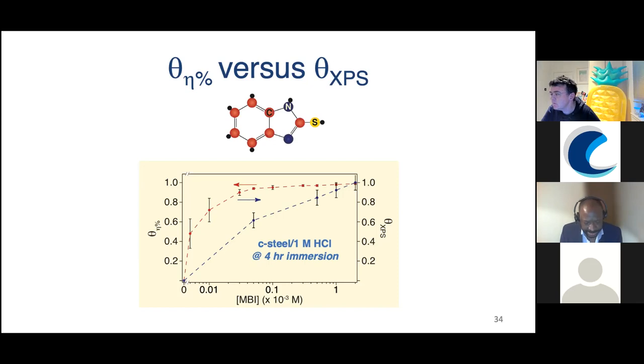Okay. Next, we have, what is the effect of temperature on corrosion inhibitor efficiency, and how can this be improved? So, usually, in many cases, when you increase the temperature, the efficiency goes down, and particularly over 120 degrees, I think, and maybe people in the industry would correct me, you start to struggle to get inhibitors to work well in general. But the efficiency generally goes down. And there are ways you could think to influence that parameter, although I think it's more difficult than addressing persistency. I think in a previous talk, sorry, I can't remember if it was in February, they were forming polymers or oligomers on the surface, which were more persistent at higher temperatures. So I think this is a way to go, for example.